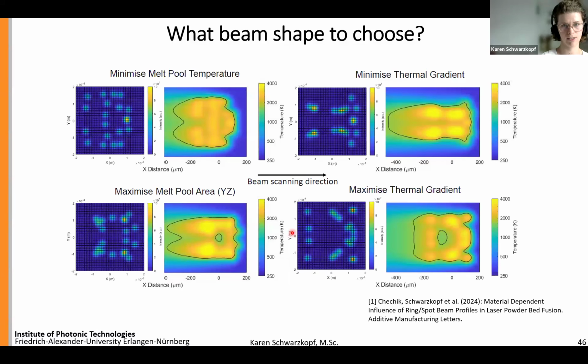And last but not least, because this question is occurring from time to time, the technology of Civan basically allows to create arbitrary beam shapes. And the question now is, what beam shape shall I use? I think this is one point that we as a community have to define and find out together, and approaches to really adjust beam shapes or find optimal beam shapes are based on simulation work. For instance, my colleague Chechik developed a heat conduction model that allows to determine different approaches like the minimum melt pool temperature and a minimized thermal gradient, and it really gives you back an intensity distribution that could lead to this minimized thermal gradient.